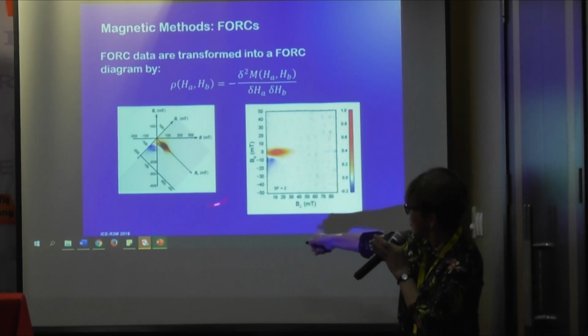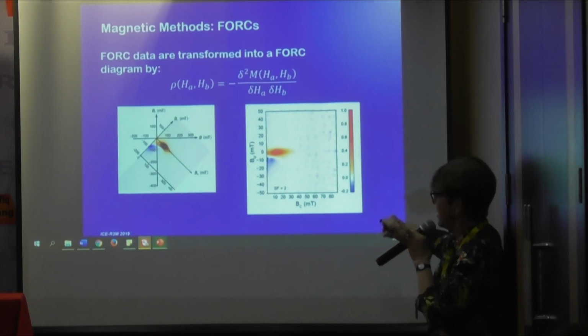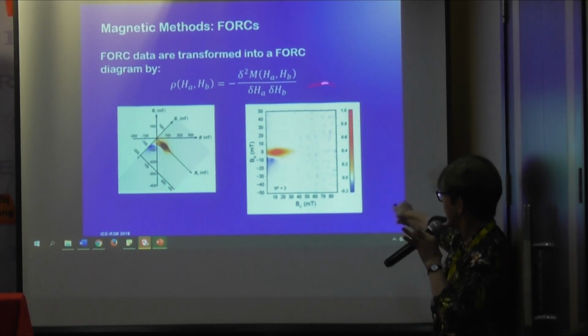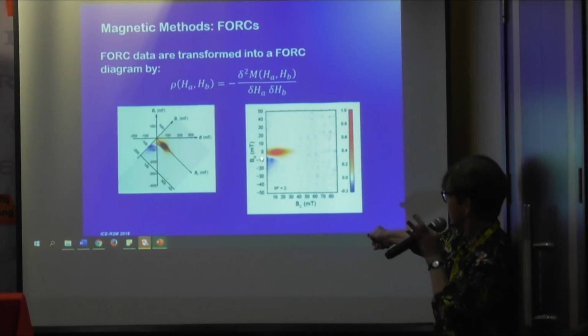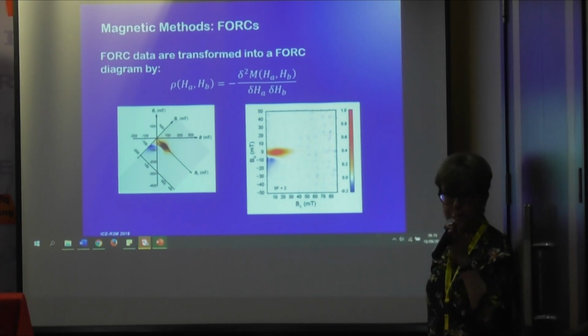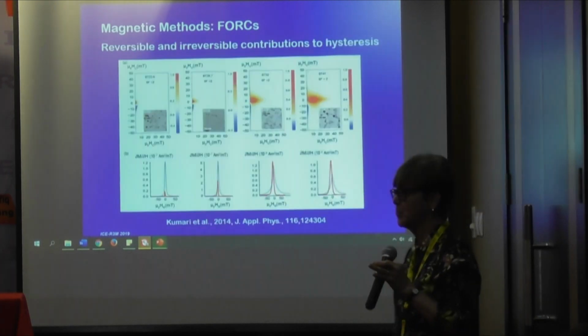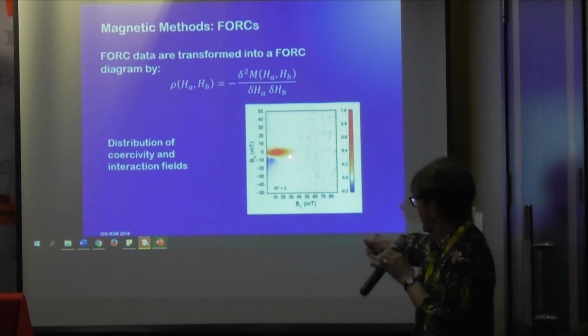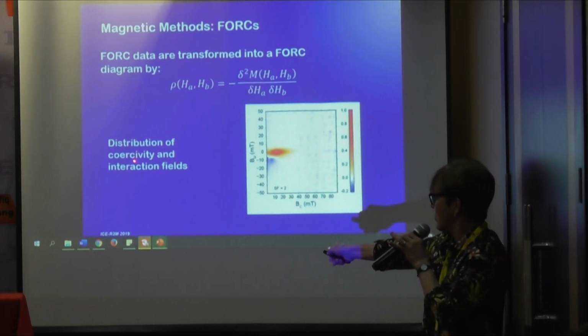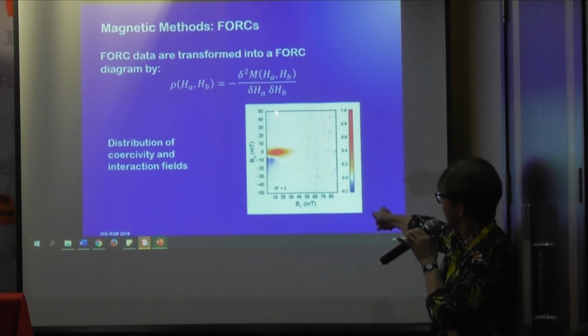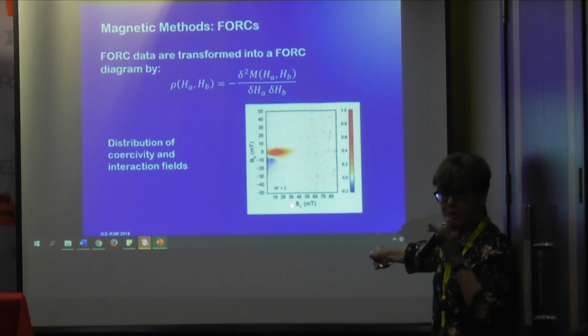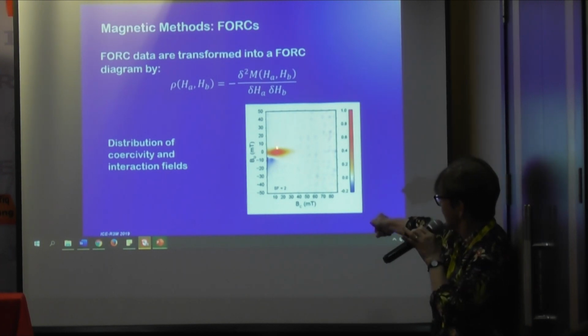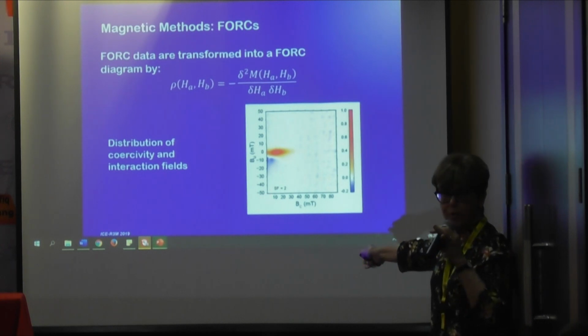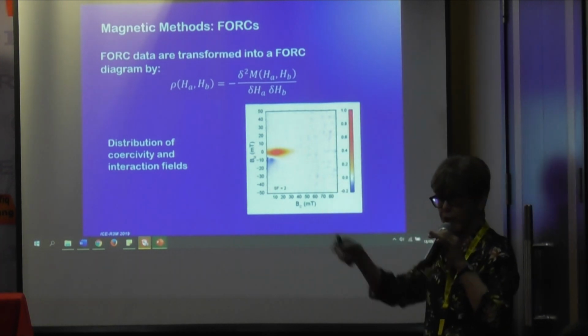Usually the physicists plot it in this coordinate system, but in the earth sciences, we plot things in this coordinate system. So you can see here I have something that has a range of coercivities going from 0 to about 30 millitesla. And this gives us the distribution of coercivity along this axis and interaction along this axis. In this case, this is a case of magnetotactic bacteria. What I have is very, very low interaction because the particles don't interact with one another, just along the chain.